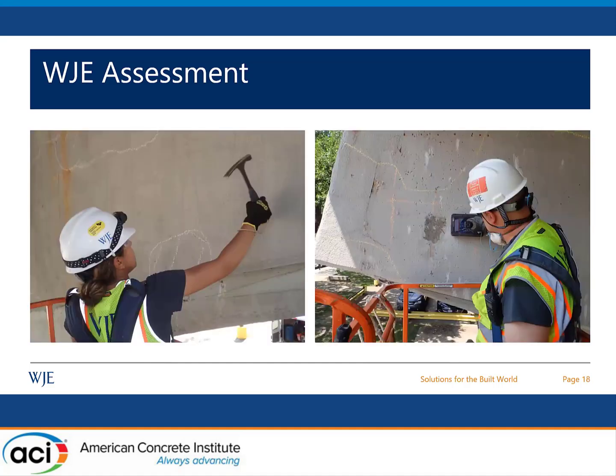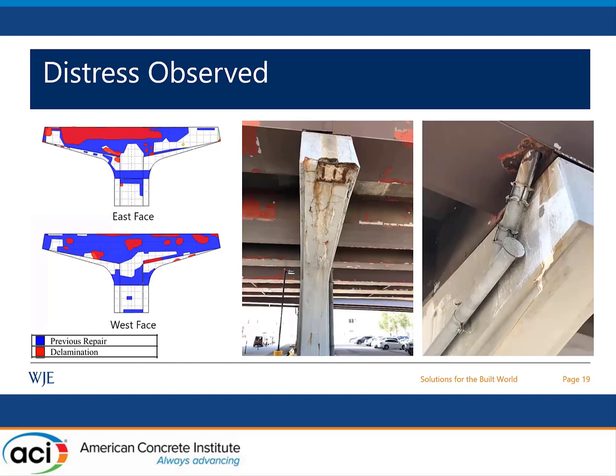Like Marwa showed in her previous slides, our field evaluation included a combination of visual and delamination surveys, GPR cover surveys, core sampling, and corrosion rate measurements. Our findings showed that there were various levels of distress currently present at the bridge piers. This is an example of one of the more severe cases of deterioration.